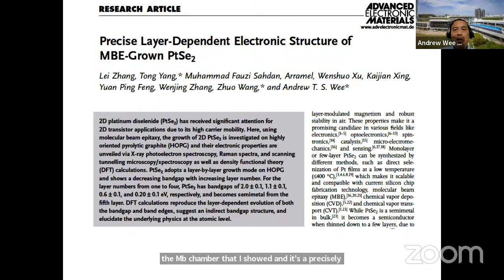One interesting thing about platinum diselenide is that it does not have a fixed band gap like silicon, with a band gap of 1.1 eV. It has a variable band gap depending on the number of layers. So the plot shown on the previous page was just at an arbitrary thickness. Because platinum diselenide is touted as a potential successor to silicon, lots of people have started working on it.